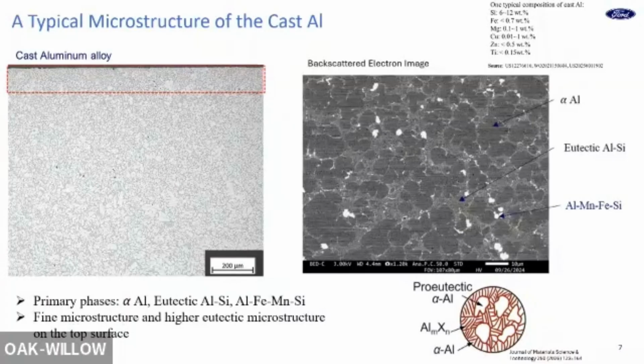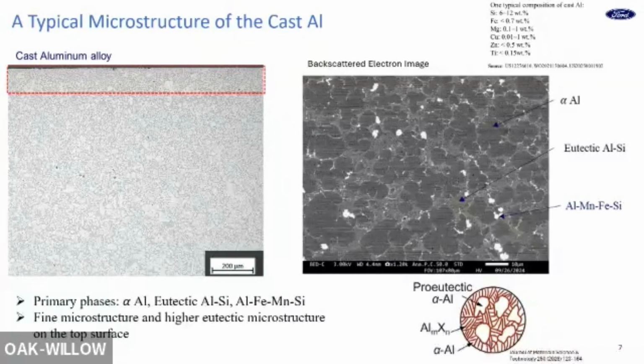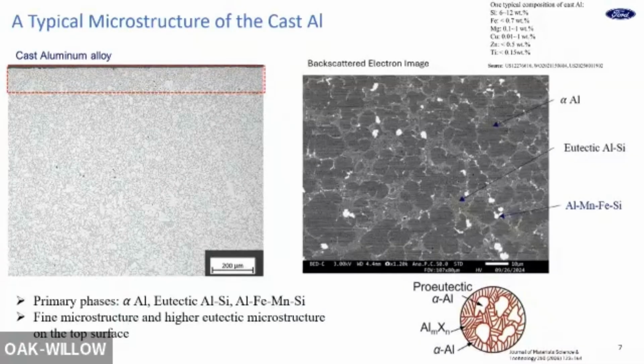In cast aluminum, there's normally a very high amount of silicon. It can be 6% or even higher than 12%, depending on the alloy you use. Because the silicon normally exists in the eutectic structure or silicon-aluminum phase. Normally it's a layer structure, silicon, aluminum. I want to emphasize this phase because we keep talking about this eutectic structure. It's a layer structure, aluminum, silicon.